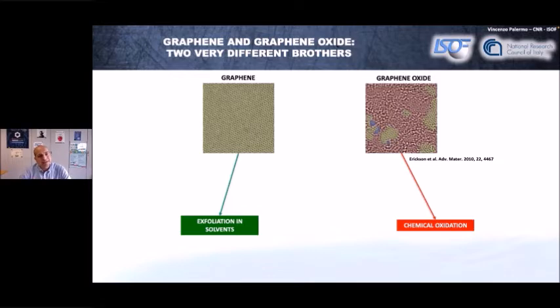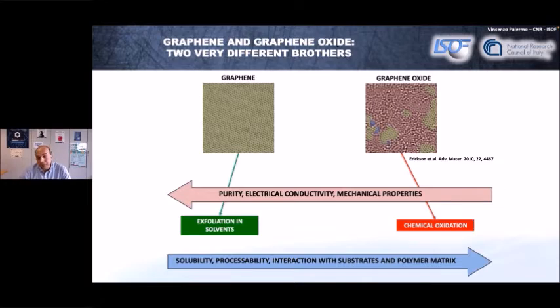If we destroy this lattice, oxidizing it, we change the perfect sp2 hybridization of graphene into something a bit more disordered. So we attach oxygens here and there, and we obtain graphene oxide. So this is basically oxidized graphene. And here we lose a lot of electric properties, and mechanical properties go down. So this is not a Nobel Prize winning material, but it has some advantages, because purity and perfection is not always a good thing. Graphene, being so perfect, tends not to interact too much with other molecules, for example. It does not like a lot of solvents, it's not very soluble, and tends to stack on itself to form graphite again.